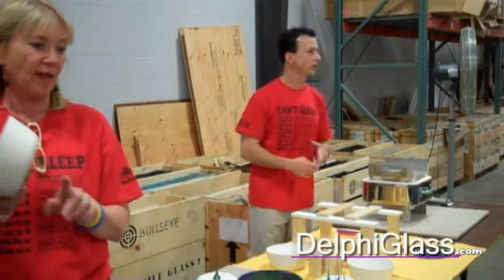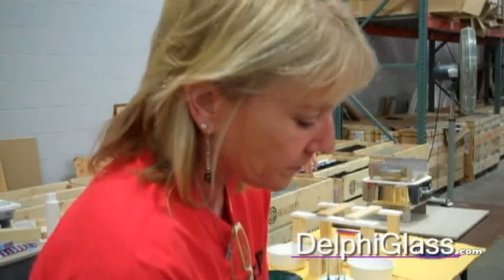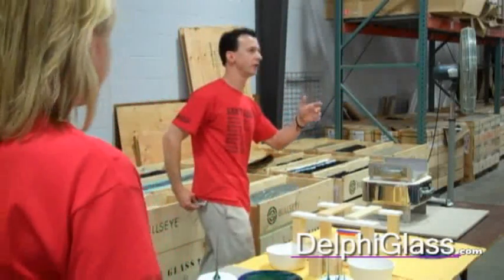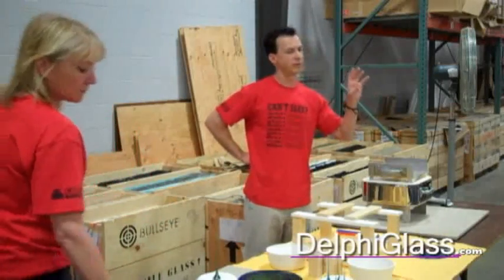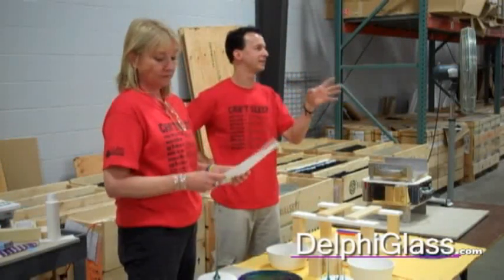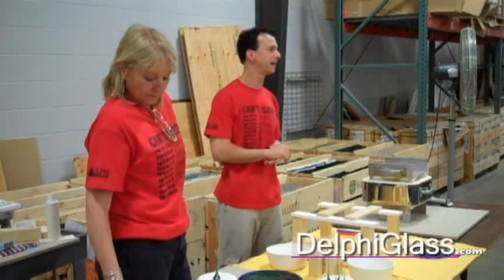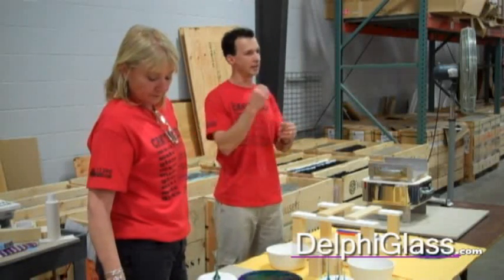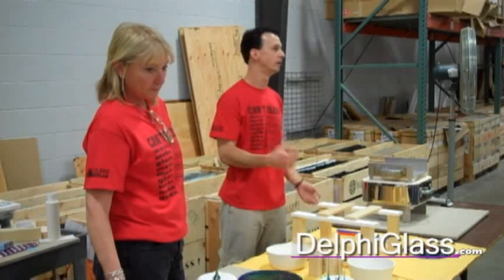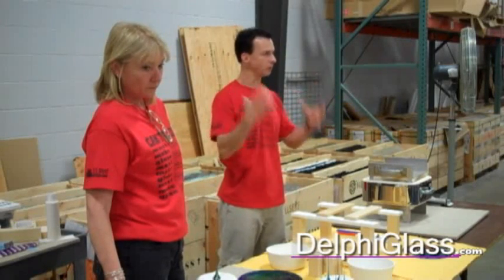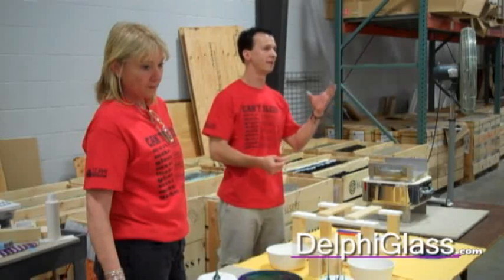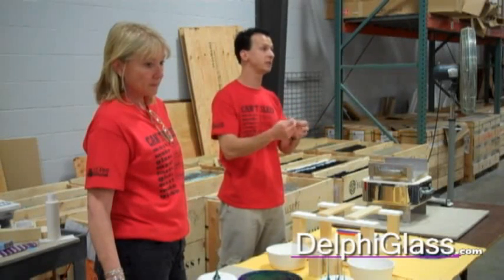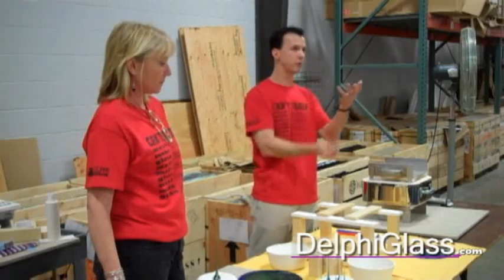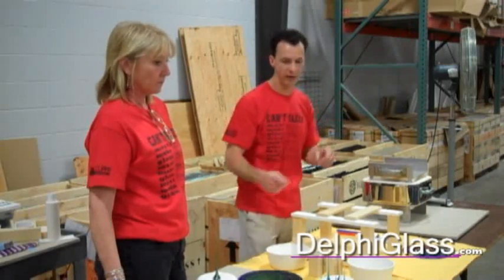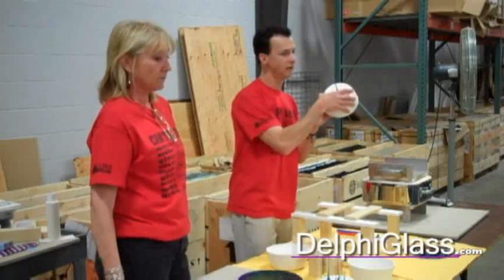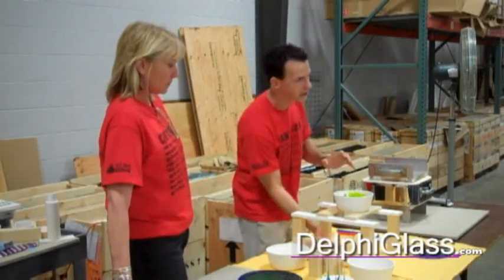Our firing schedule, if you looked at it, I think we said that we take it to 1600 and we hang there for about 45 minutes to an hour. The reason for the length of time really has to do with how much glass you've put in the pot. I have never been able to totally drain a pot of all the glass, ever, and I've tried, holding it for a real long time at a really high temperature. Eventually there's not enough weight of glass for it to want to drip through the hole. And so you'll always get this that will attach to your disc.